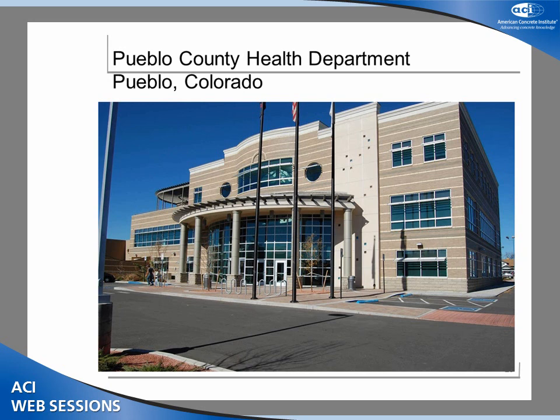The local ready mix producer developed concrete mix designs with local and recycled materials and Portland limestone cements, including mixes that ranged from 15 to 25% Class F fly ash, in the footings, foundations, flat work, and also above grade walls. This was another project where all strengths exceeded design requirements, and the finishers also noted that they enjoyed the improved finishability. Sometimes in Colorado we can lack fines in the sand, and we often get unsolicited compliments from finishers, which sometimes are hard to come by with Portland limestone cements. This was certified as LEED Gold.